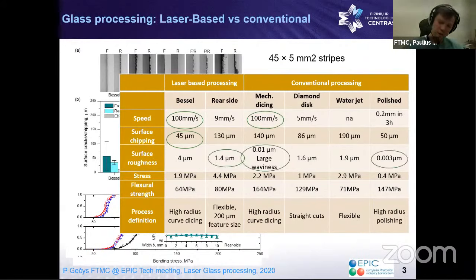If you are really interested in surface roughness, of course, if you want really high optical quality, you need to polish your surface. But rear side processing gives you a fairly good roughness of about 1.4 micron. Mechanical dicing also gives you quite low surface roughness, despite having really large surface waviness. We also tried to measure stresses inside the glass induced by these techniques. And we saw that if you need really low stresses produced by processing, you might need to use diamond disc cutting, or any other technique, and then polish the affected region.